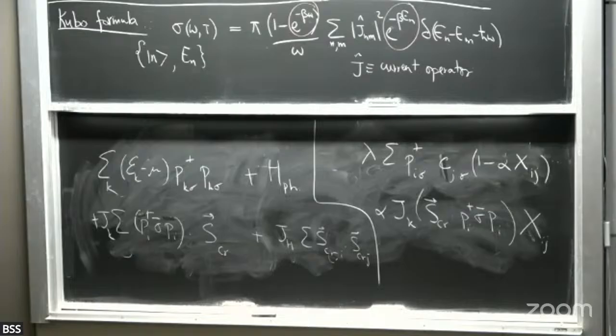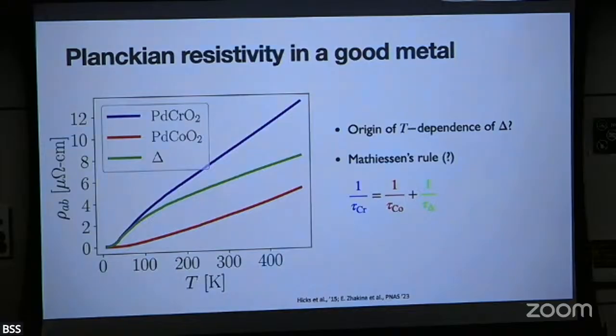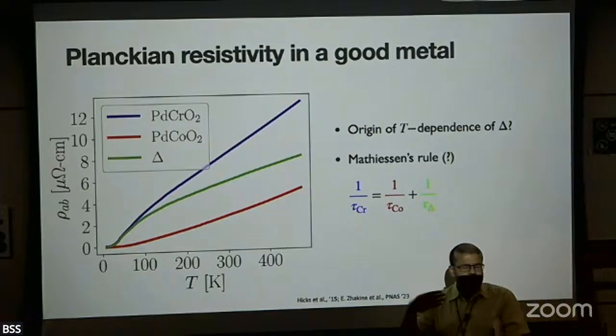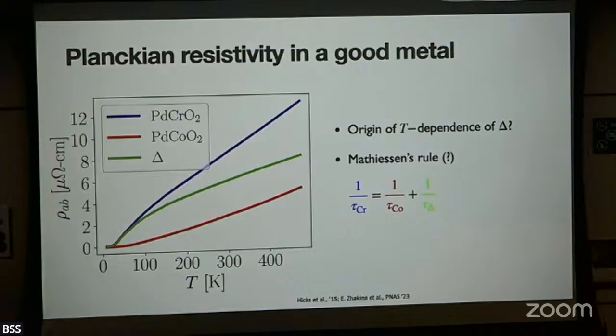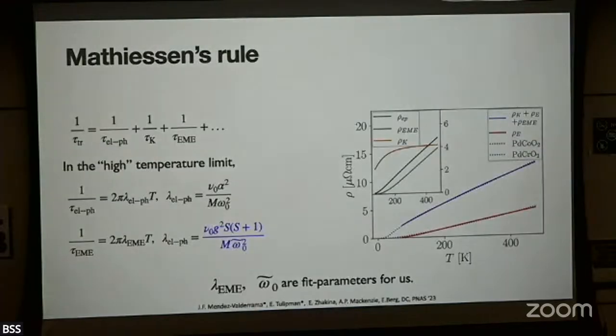Okay, with this we're basically done. So we're again going to assume that this high temperature regime where you're seeing the T-linear resistivity is associated with this out-of-plane phonon displacement being in its quasi-elastic regime, where the phonon occupation is given by just T. But the good thing is you can do a much more detailed calculation, a full-blown Boltzmann calculation. This is what the dotted lines versus the solid lines represent. The dotted lines are data. The solid line is an actual Boltzmann calculation with all the known microscopic couplings, with the only fit parameters in the theory being the strength of this magnetoelastic interaction and the characteristic frequency of this out-of-plane phonon displacement.